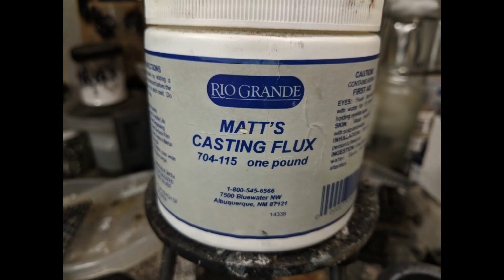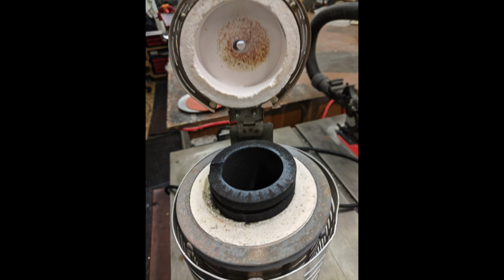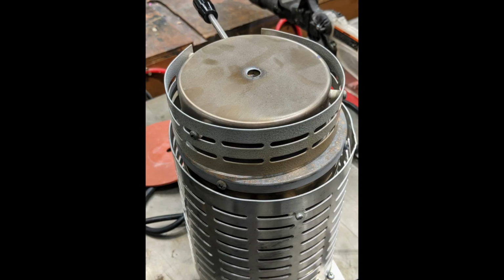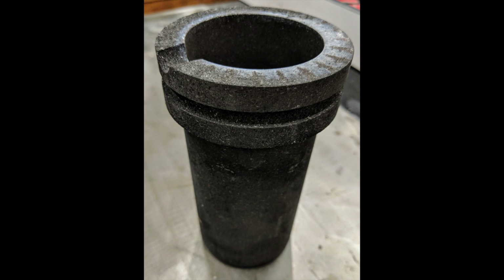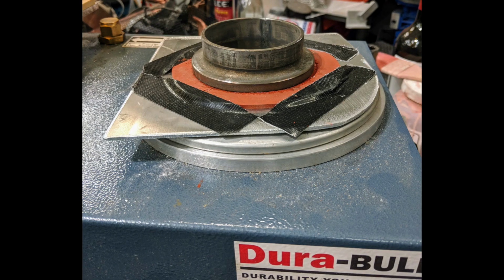I placed the gold in with a small amount of casting flux. Once this was in the vessel, I closed the top and allowed it to reach casting temperature. The flask was then opened and stirred with a carbon rod, and the flask was then taken over to my casting machine, where I'd taken the vessel out of the kiln, placed into the casting machine, and I poured the gold into the casting machine after a vacuum had been pulled.